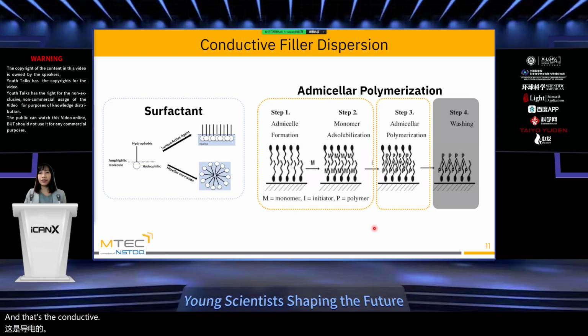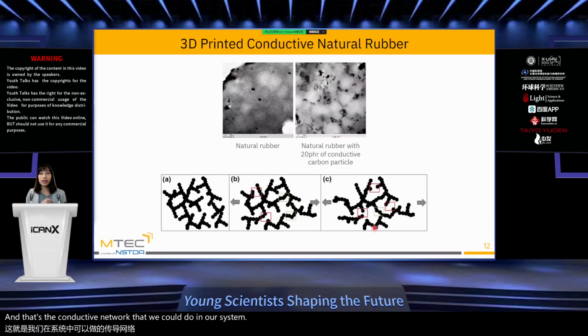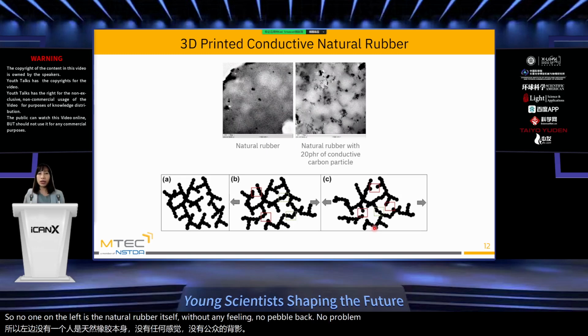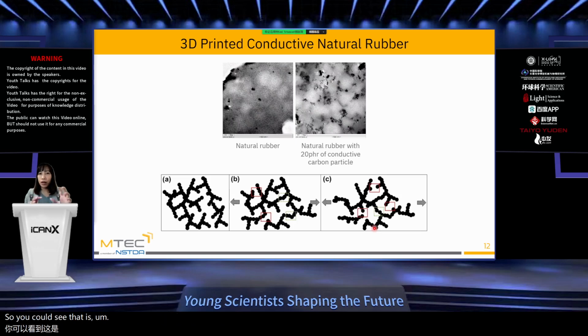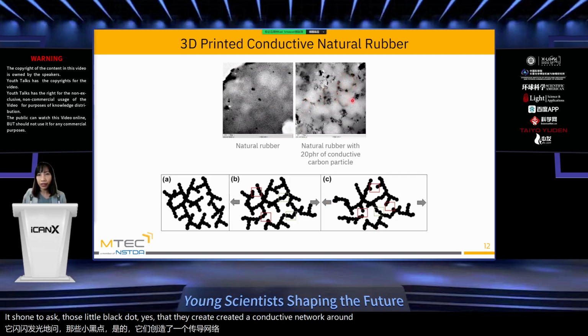And that's the conductive network that we produce in our system. The picture on the top is actually the TEM images. The one on the left is the natural rubber itself without any fillers, no carbon black, no carbon nanotube. You can see that it looks like a lot of spheres, like a pack of balls in your system. When you include the conductive carbon particles, they show up as those little black dots here that create a conductive network around the sphere. The sphere is actually the natural rubber particles, and you can see that the carbon black forms the outer surface of the sphere, and then it connects to each other.